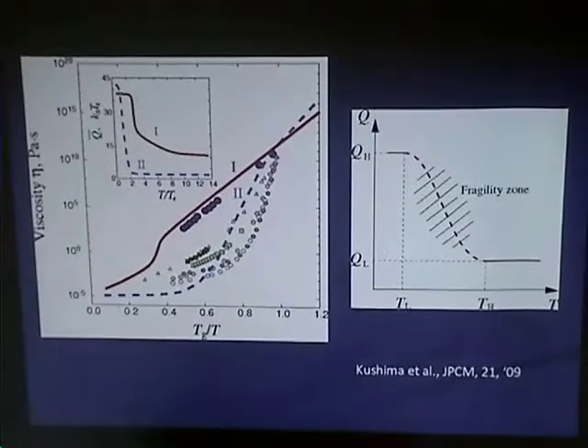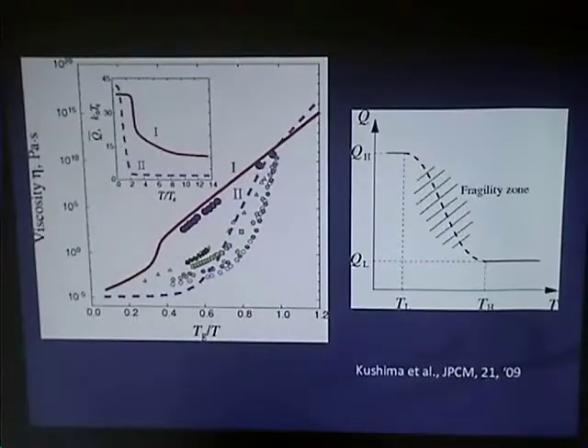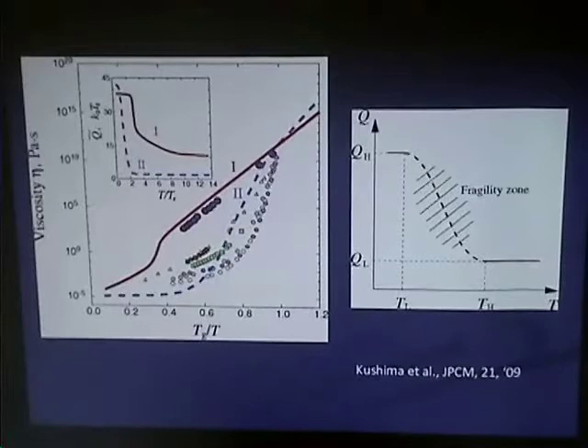So in this work, we've been looking at polystyrene films that are less than 90 nanometers, down to 10 nanometers or even less. And in the glass regime, we have a way of looking at relaxation there.